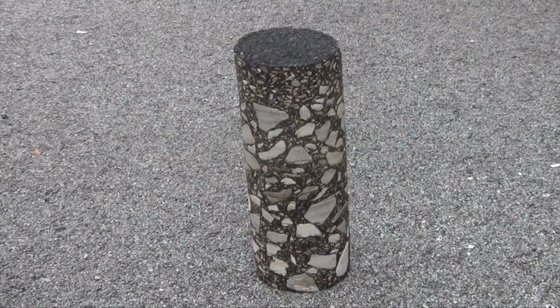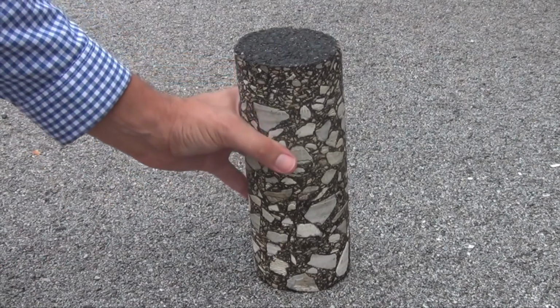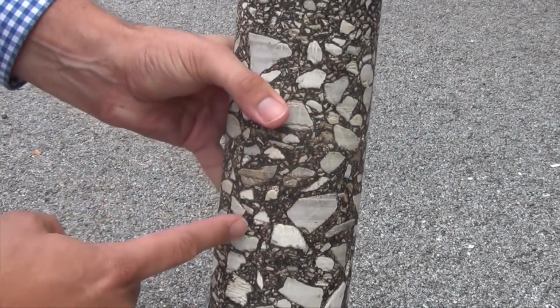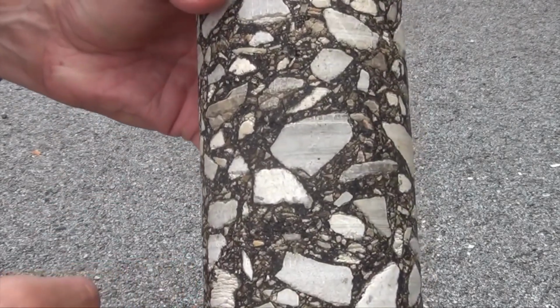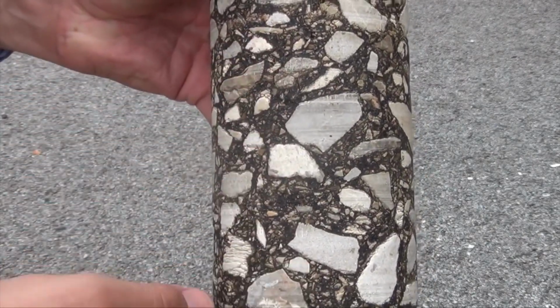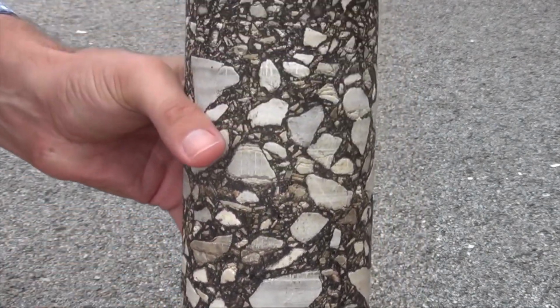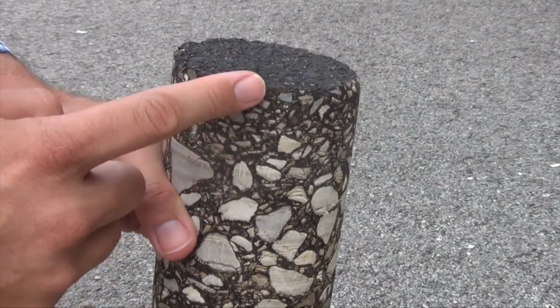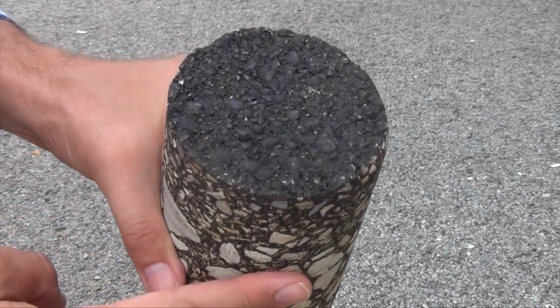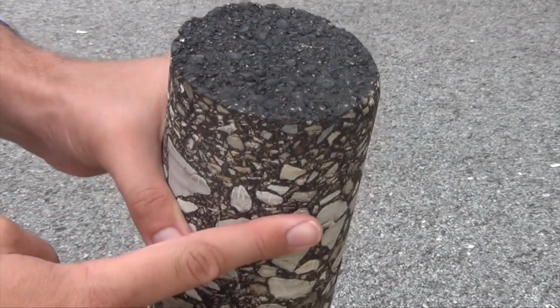This is a core drilled from a roadway that shows a cross-section of the asphalt within. You can see a coarse mix of asphalt in the lower section, or base course, and a finer mix designed for the surface layer. This fine mix is less permeable and keeps water from penetrating down and causing cracks to form.